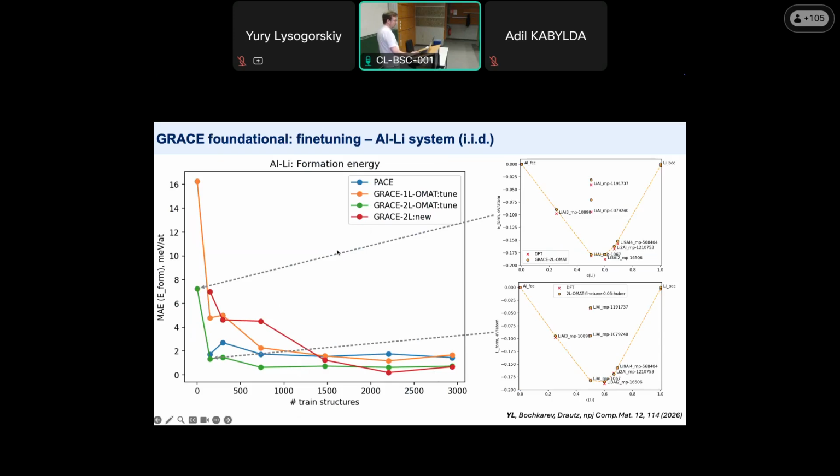Also, if you compare, for example, this red curve versus this green curve, the red curve has the same model complexity but is trained from scratch. This demonstrates that if you fine-tune the model, contrary to training from scratch, you achieve these metrics very fast and you can be very data efficient. Combining with the uncertainty quantification mechanism from the previous topic, you can even optimize the selection of this necessary 5% of the data to achieve the best coverage with the smallest amount of data.